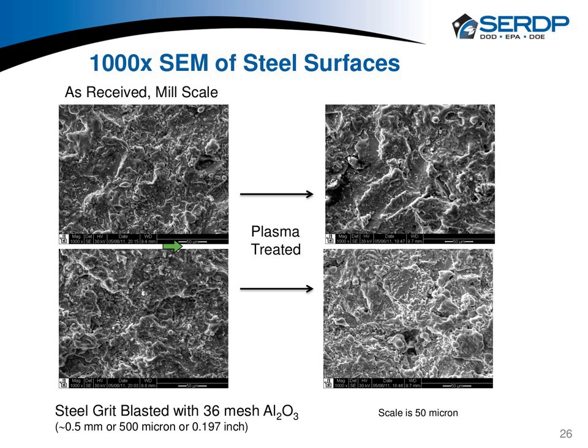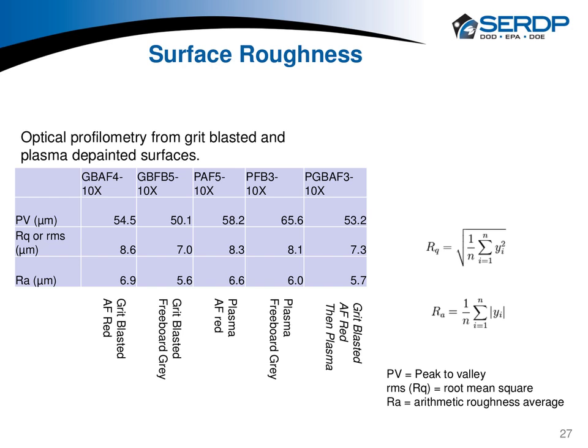One of the questions that was raised in the statement of need was, does the plasma alter the topography? And there are reasons for that roughness: mechanical interlocking, increasing the surface area for bonding, ensuring that the paint longevity will last. Well, these surfaces were treated with plasma, and visually, both in SEM and optical, and in a couple of other techniques that we used, we couldn't find any physical changes with respect to the topography. And that makes a lot of sense too. Once an oxide is formed, well, then what's next for the plasma? There's no more work for the plasma to do, and so the surface essentially self-passivates, if you think about it that way.